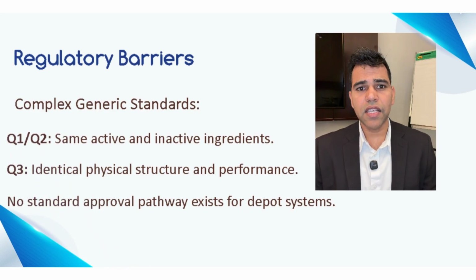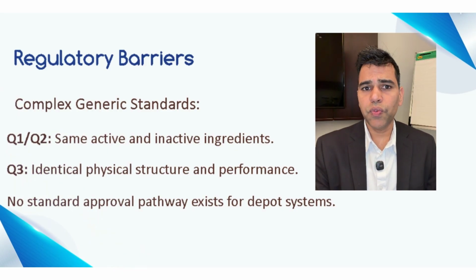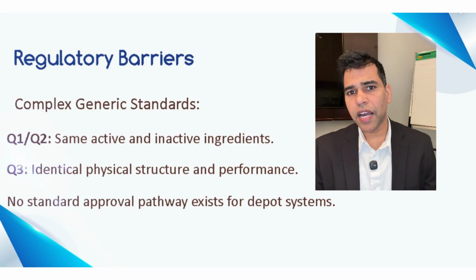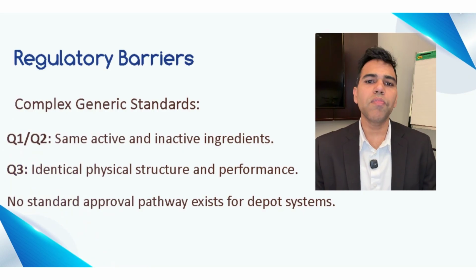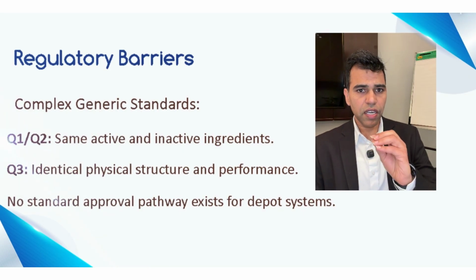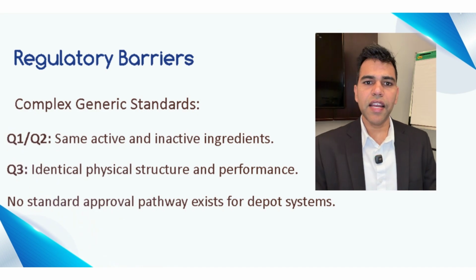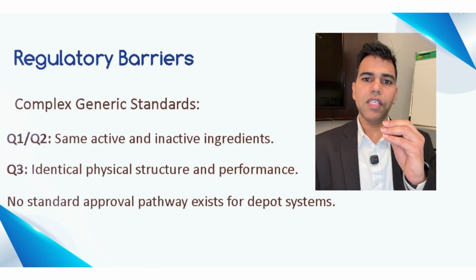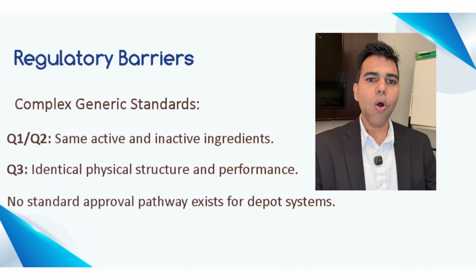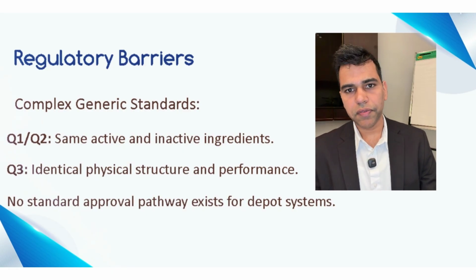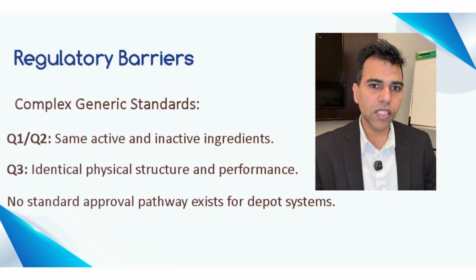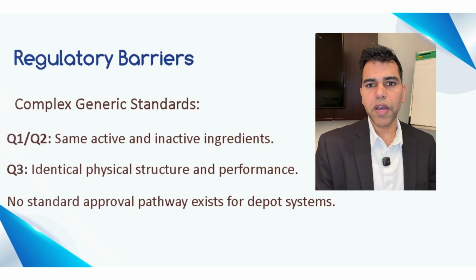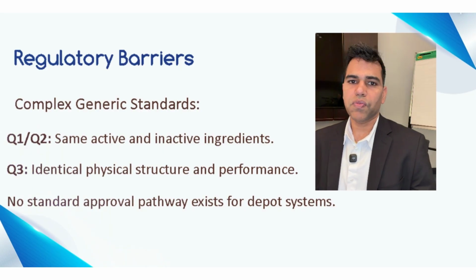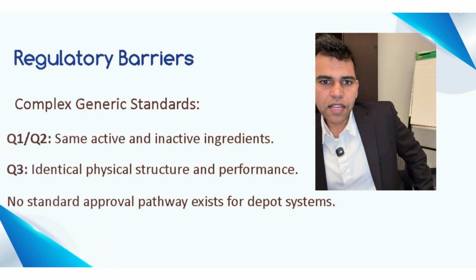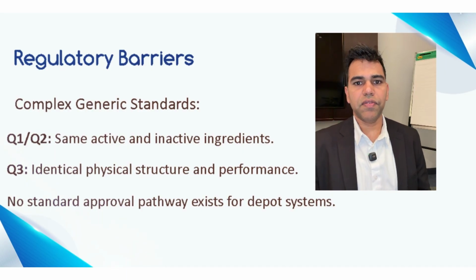Leuprolide acetate is a 9 amino acid peptide. Its interaction with the PLGA, ionic, hydrophobic, conformational, is far more complex. The burst release behavior, the degradation kinetics, the physical stability inside the polymer matrix, all of these are peptide specific. IVIVCs developed for naltrexone microspheres cannot simply be transferred to leuprolide. The science has to be rebuilt from scratch.